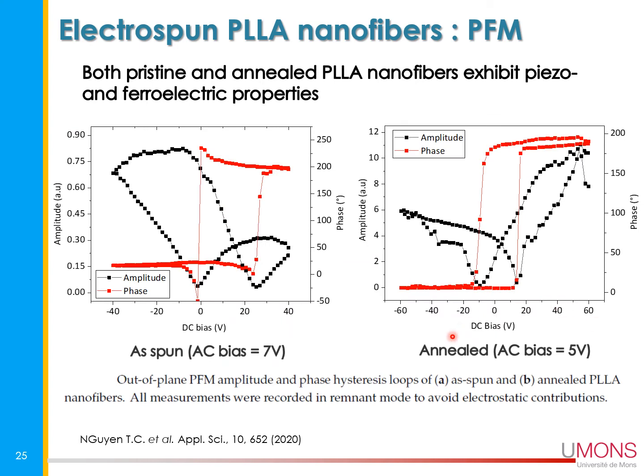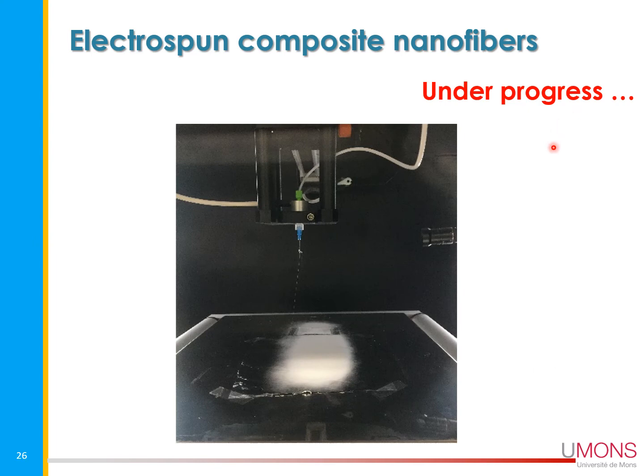And this is what you observe with as-spun nanofibers. So we have this butterfly shape and this hysteresis loop for the phase and the amplitude for the as-spun and for the annealed sample. So it's possible to measure some piezoelectric properties out of this PLA nanofiber. The problem now is to calibrate and to be sure that we are measuring correctly those PFM properties or piezoelectric properties.